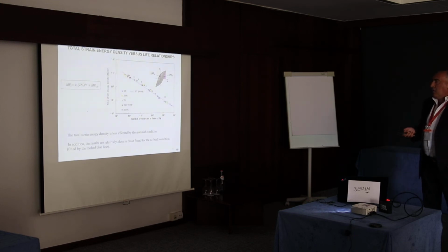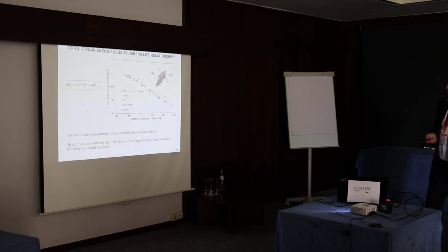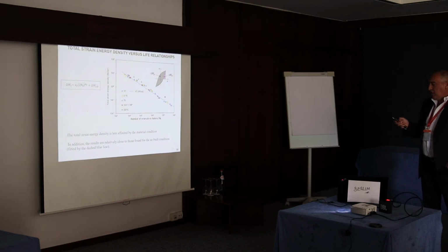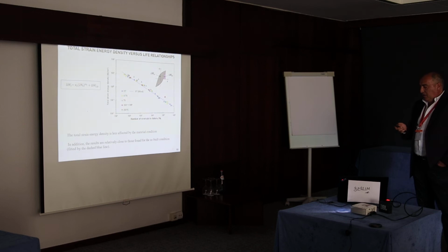Finally, we can plot the total strain energy density versus life relationships, and in this case, the density is less affected by the material conditions. In addition, the results are relatively close to those found for the as-built condition, fitted by the dashed blue line. This dashed blue line is for the non-treated material, and the other ones for the treated materials.